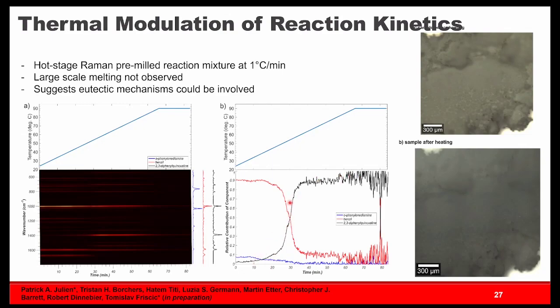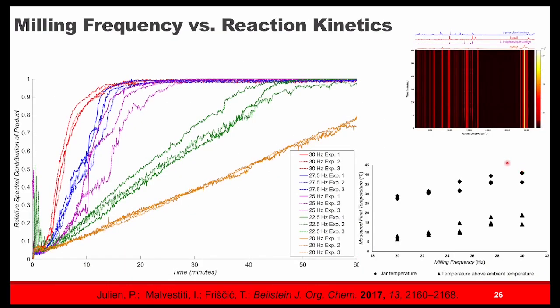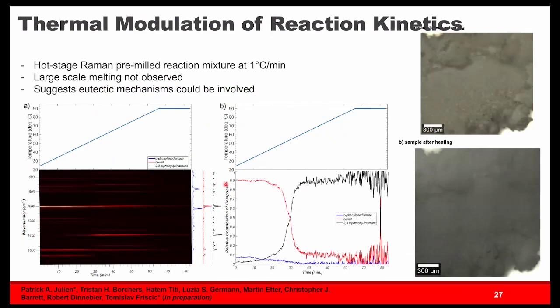And actually, if you look roughly at where this sigmoid is starting, you're in the 40 to 50 Celsius range, which is exactly the temperature that we're starting to hit when we're milling at higher frequencies, and we see this kind of sigmoid. So I think this is really strong evidence, and it is known for this reaction that there is a deep eutectic which can form. I think we're not at the eutectic point yet. We don't see large scale melting. It goes in as a solid.